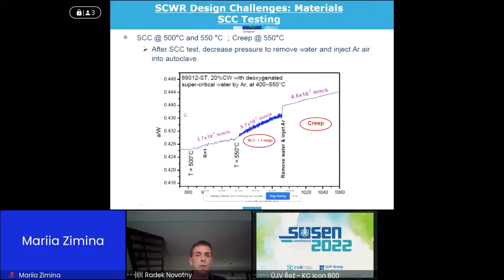There is also another aspect, and this is the study of Lefu Zhang from Shanghai Jiao Tong, one of the latest, where he performed the test in 500 degrees C supercritical water, and he was measuring 3.7 times 10 to the minus 7 millimeters per second crack growth. Then after 1,000 hours he changed the media to an argon atmosphere, and he measured 2 times slower crack growth, but still he measured growth,